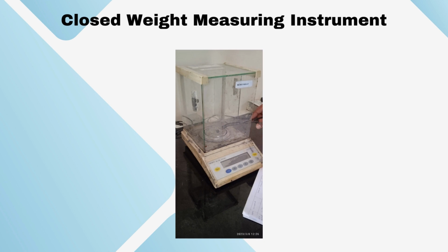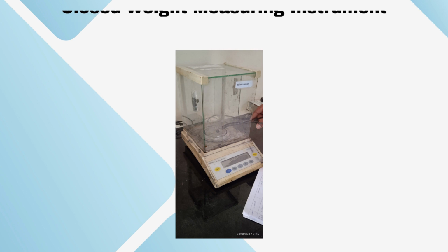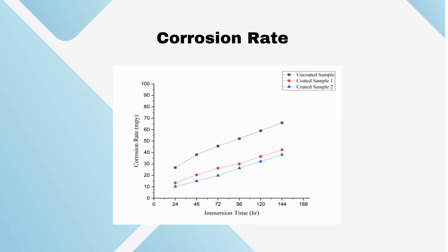All three samples were immersed in separate beakers containing 1 M HCl acid solution. The corrosion rate of the uncoated sample after 24 hours is 26.8 mils penetration per year, whereas the coated samples have lower corrosion rate values of 13.4 mils penetration per year and 10.8 mils penetration per year for 15 minutes and 30 minutes anodized samples respectively.